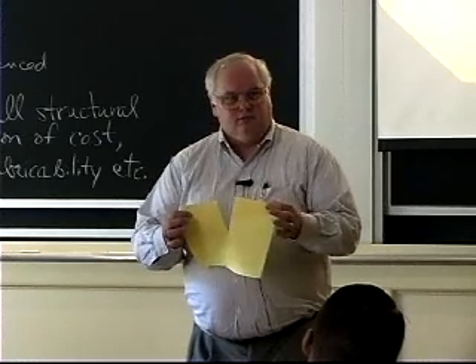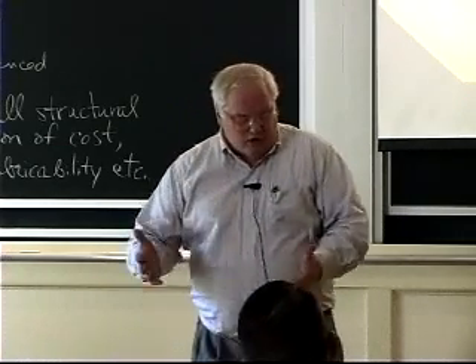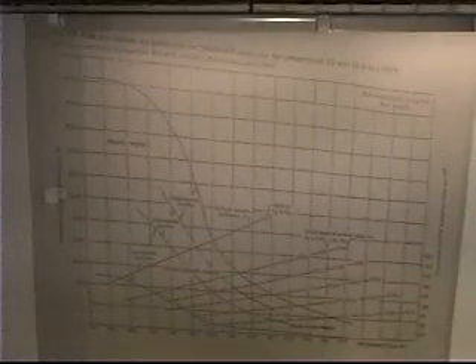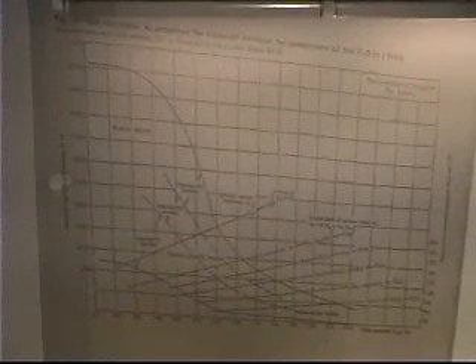If I put a defect in there, it takes ounces. That defect, that flaw, that initial crack significantly weakens the material. And we'll talk about fracture mechanics later, but for a structural material, you not only want strength, you want toughness as well. And this is the fracture analysis diagram developed by Dr. Pellini after World War II. People didn't understand fracture toughness very well during World War II.